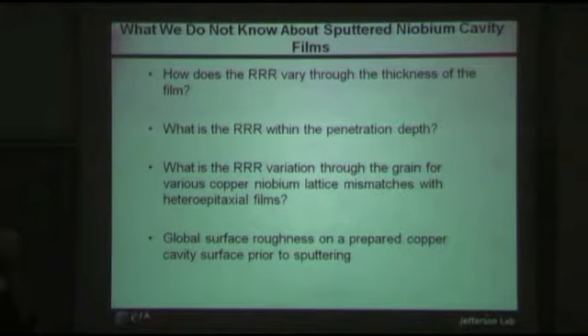There are some things we don't know about sputtered films. When we measure RRR either on an insulator or after removal from copper, you're measuring the average RRR of the whole film. And we have no idea how this varies from the onset of nucleation, where we know the RRR is extremely low as the film gets organized, to its final value at the penetration depth, which is what you care about. So what is the RRR at the penetration depth?